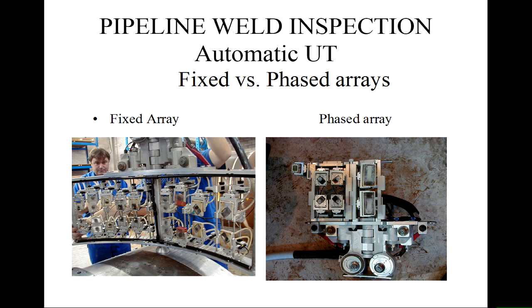The other thing you can do is have what we call a phased array, and we only have a few sensors in this case, but we're measuring continuous variations as you go around the weld, and then we're looking at phase changes between the ray that goes out, if you like, the sound wave that goes out, and when it comes back. So you're interfering the two, and you're measuring phase differences, and that gives you an indication of the scattering that's taken place on the way. So that's a much simpler sensor, but you're relying on that moving and collecting lots of information as it moves to give you the results.